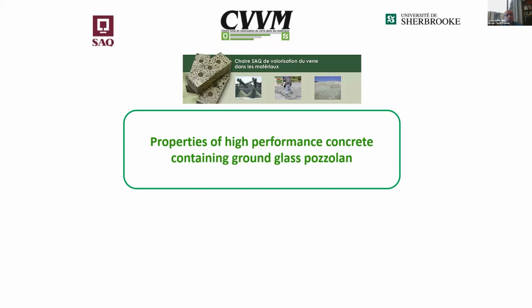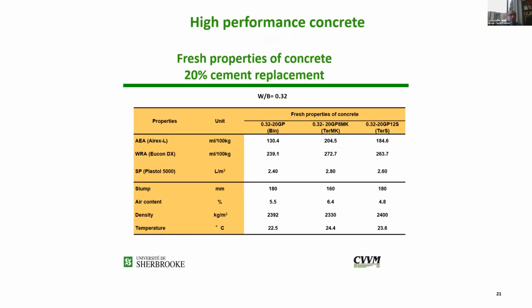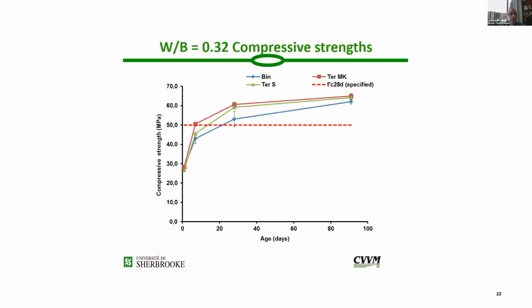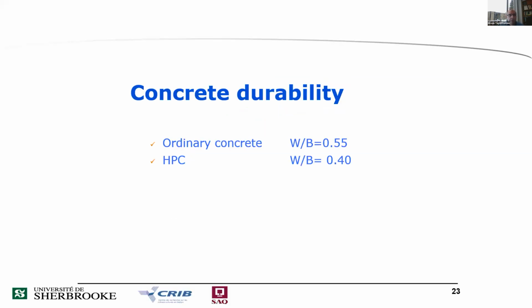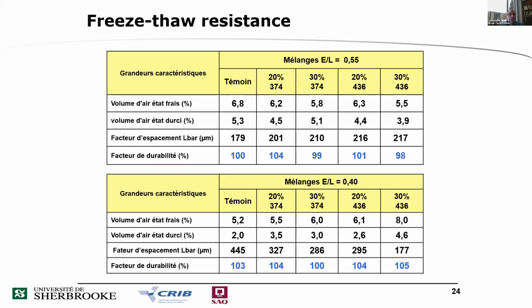In a high performance concrete, we did a lot of work here, and this work was done mainly by Zidal. So 20% of cement replacement. And we can see here that the compressive strength is also good, and it increased, even in binary or ternary mixtures. For the durability, of course, freeze and thaw depends on your durability factor.